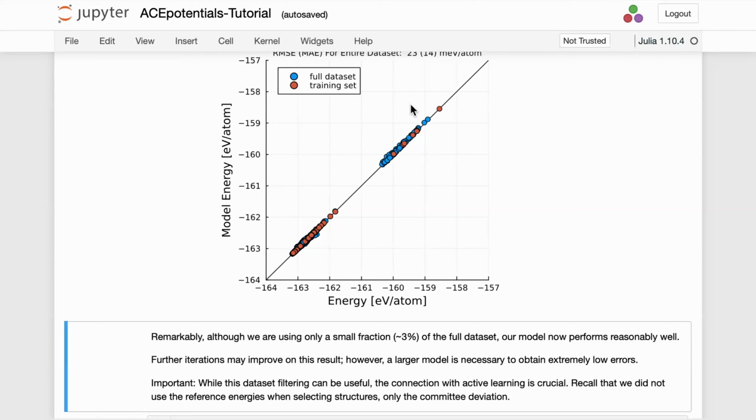So we're using it as a sort of example. But you can imagine building a model that's fit on a small number of DFT calculations and starting an MD run, maybe, and monitoring the uncertainty, the model's confidence as the MD goes forward. And then maybe the MD trajectory wanders into some very unknown region. The model says, I'm really unconfident. We stop, we add that config to the data set. And hopefully with a minimal amount of DFT calculations, we can get to a robust model, yes.